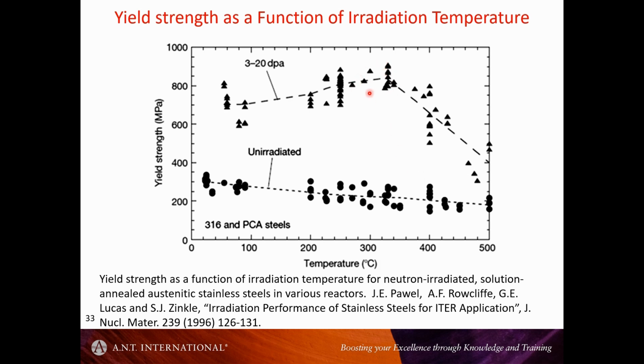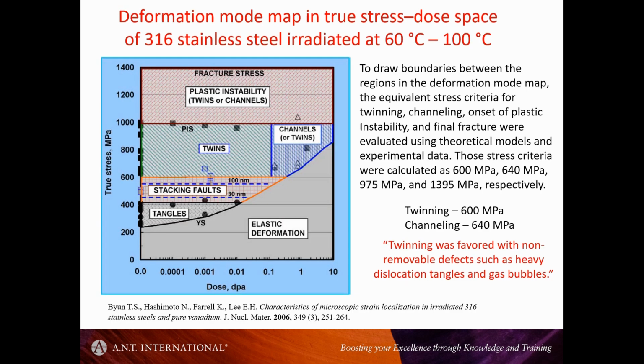There's a sweet spot here around about 300 degrees C, and at lower temperatures, because you get a bit more recombination going on, you can reduce this density as well. And again, that's counterintuitive, but not if you work with radiation effects and what the supersaturation of the point defects means when you do rate theory calculations.